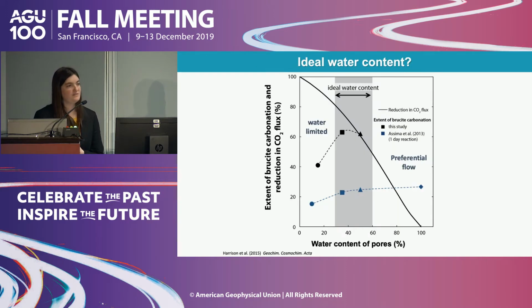And so in summary then of these observations and what they mean for CO2 storage, it appears that we may have a sort of ideal water content that will maximize the amount of CO2 stored. For example, it's expressed here in terms of the extent of reaction on the y-axis versus water saturation on the x, with an ideal water content shaded in gray. So for this particular reaction, between about 35 and 60%. So we have enough water that reactions can progress till they finish, but not so much water that we end up with these preferential flow effects. And this is going to be relevant for gas-driven reactions in general.